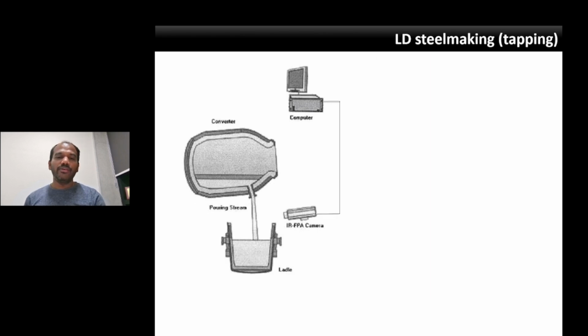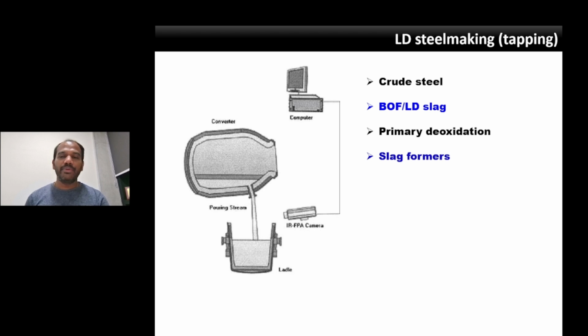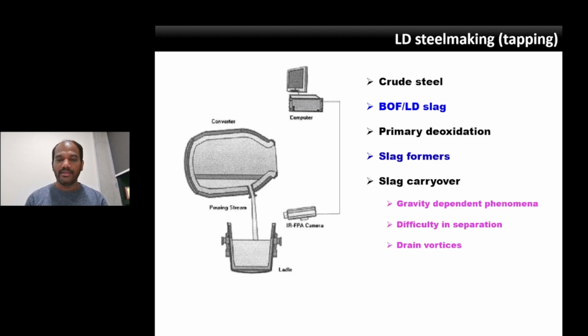So our work primarily focused on the tapping process, that is the transfer operation that involves the transfer of liquid steel from converter to the ladle. We know that crude steel is produced along with BOF slag, and during tapping, generally there is a practice that the deoxidizers are added, aluminum, silicon, manganese, and some amount of slag formers are also added, like calcium aluminate slag, and some synthetic slags of different compositions.